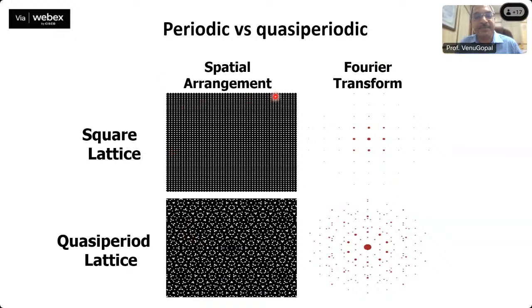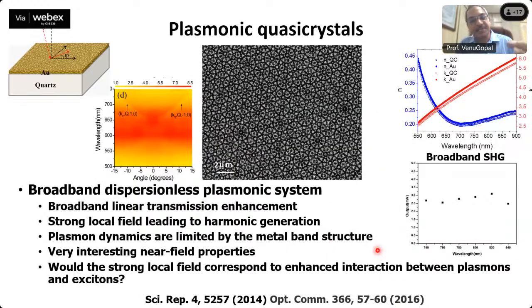So we also developed this quasi-periodic structure. If you have an arrangement of scattering elements in a square lattice, the Fourier transform is a square lattice, and this is a discrete structure. However, when the same number of scattering elements are arranged in a 5-fold rotation symmetry, you see a very dense K-space, which allows you to have polarization independence. Then you have broadband response from these structures. There is no incident angle dependence also.